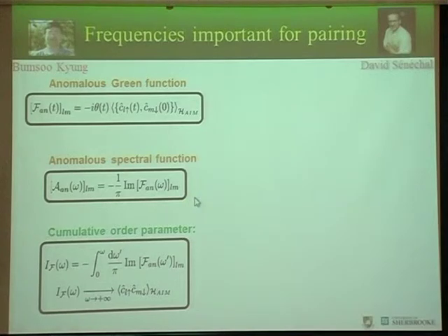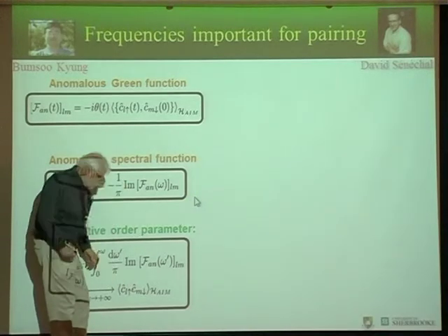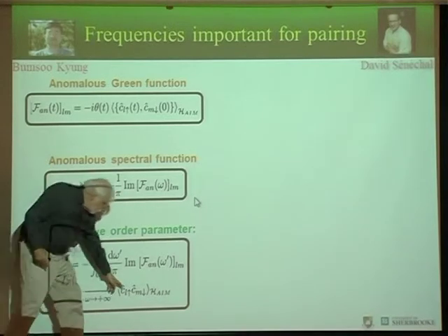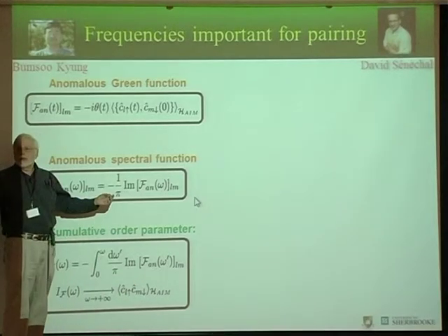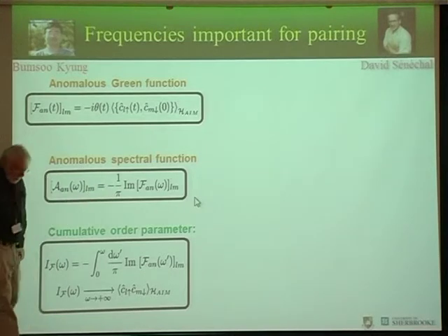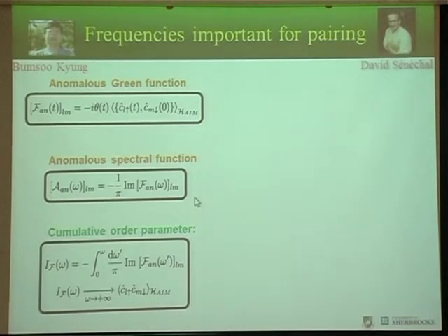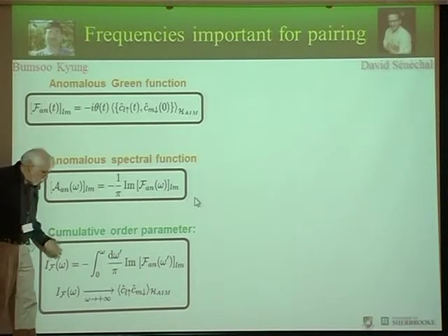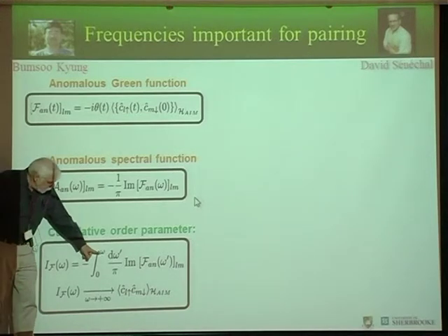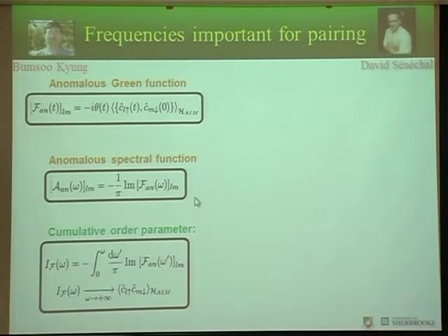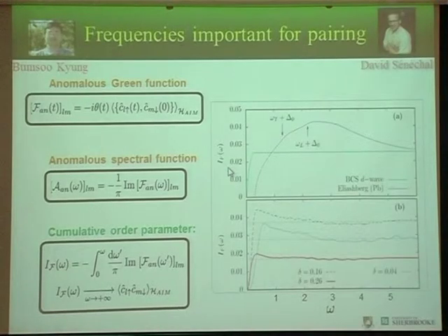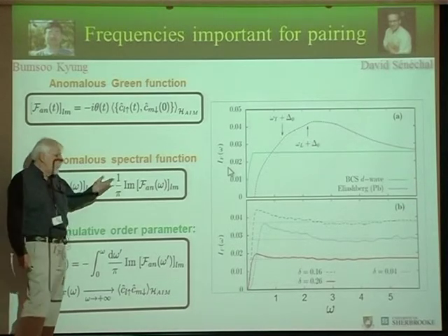If you look at this equal time correlator as a function of distance, as a function of L minus M, it will give you the superconducting coherence length. It will decay with this length. So what we suggest here is that we should look at this frequency dependence. In other words, we cut off the integral at some frequency omega, and that should tell us what frequencies are important in pairing. That's an unusual way to look at this, but to understand it, we look at the familiar cases.